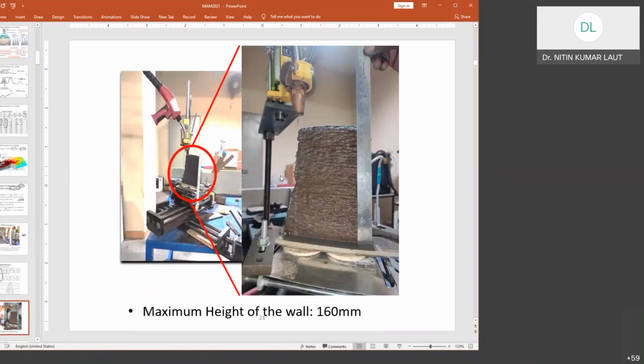So here you can see the proof of the output, what we got. You can see this heap of layers deposited, okay? And this is all 316L, sorry, 316LSi. This has been deposited layer by layer, and it could go up to 160 mm, but this is not the limit. This 160 mm is because of the constraints of our Z movement. If we could increase the Z movement, obviously there are chances that this height could be more than 160.